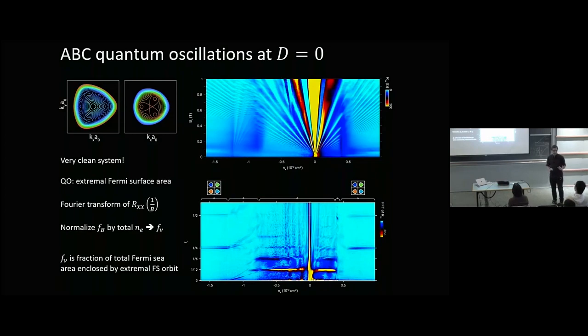Nothing is particularly special. As you lower the density, you see that this quantum oscillation depins from 1/4, and it's joined by another one at very low density. And actually there's a sum rule which returns the Luttinger volume if you take this frequency and you subtract this frequency and multiply by 4. And that's what you expect as you go through this Lifshitz transition, which is again there in the single particle band structure. It's nothing too interesting. But you can see it really clearly that there's this broad range where you've gone through this Lifshitz transition. Now you have an electron-like as well as a hole-like Fermi surface.